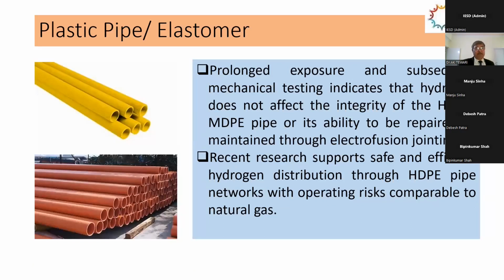Regarding the PE pipe, because of the low pressure distribution, we go for a combination of a steel pipe as well as a low pressure polythene pipe. And the study also indicated that as such there is no effect; they have taken a study for 1,000 hours or something like that for various pressures, at various institutes, and as such no problem was found. And they indicated that safe and efficient distribution of natural gas along with hydrogen mix can be done with the PE pipeline system too, which is operating at a lower pressure.